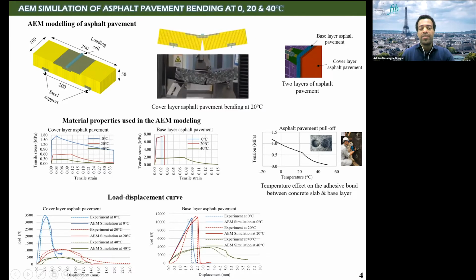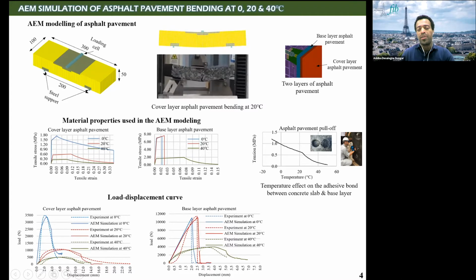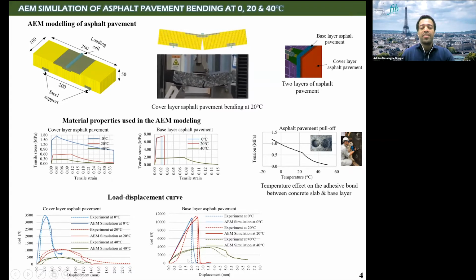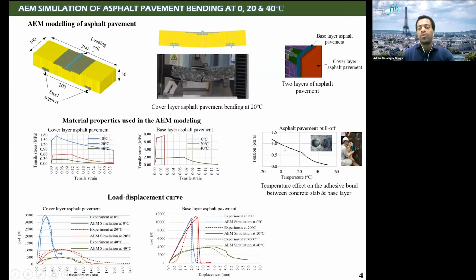It increases linearly, then it shows brittle failure without any deformation. But when the temperature is increasing, its strength is decreasing, but it shows ductile failure. Another temperature-dependent material is the tack coat, which is an interface bond material between the concrete slab and the base layer and between the two asphalt pavement layers. And a pull-off adhesion test was carried out at different temperatures, and you can clearly see its bond strength, which is highly temperature dependent.